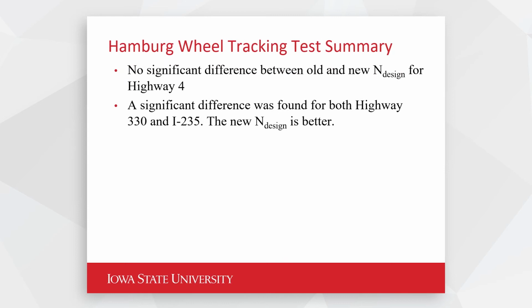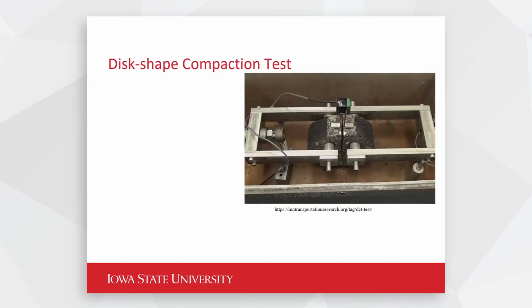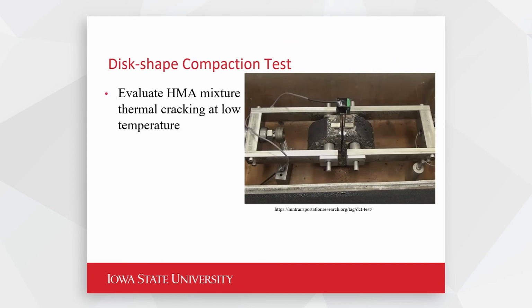We did find a rather significant difference for both Highway 330 and I-235. The new design criteria is certainly better, and we're not compromising performance on our low volume roads. The last performance test we ran was the disc-shaped compact tension test for low temperature cracking, and we can see the DCT results on the next slide.